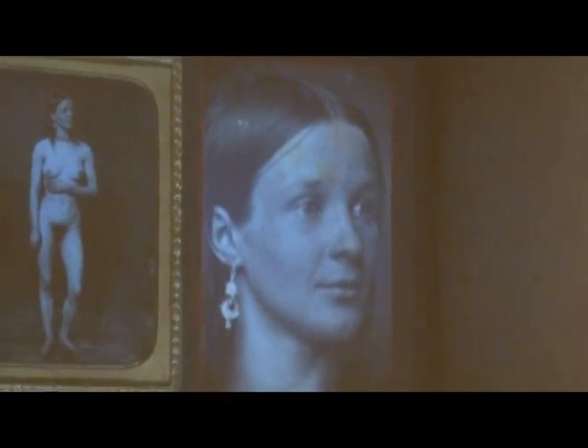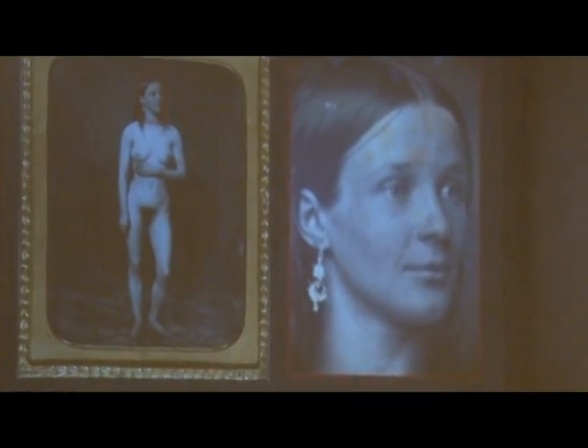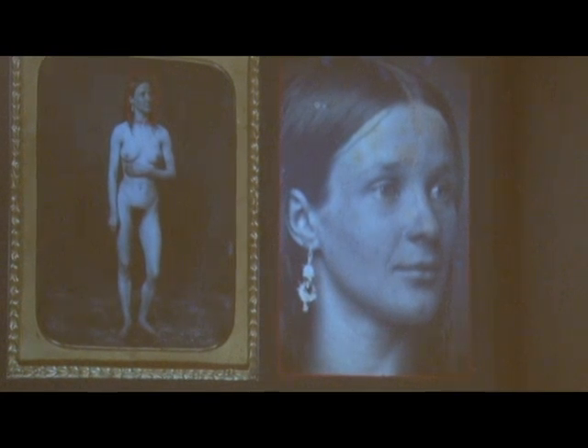And once this problem was understood, thiourea treatment became obsolete among photography conservators, and it has not been used since 1979. What happens with thiourea is that the chemical interaction that makes the tarnish go away actually forms a compound that sticks really close to the daguerreotype, and it cannot be washed away really easily. And the material is invisible at the time, but it continues to interact with the silver over time and eventually develops into these yellow spots.